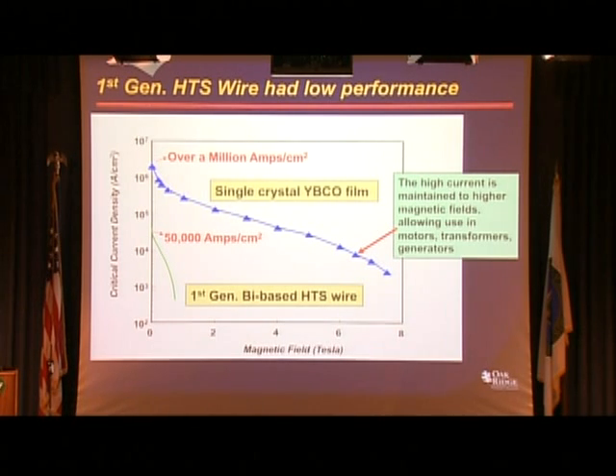What we wanted was a blue curve, which is really of a YBCO film deposited on a single crystal strontium titanate. You can see that it had a current capacity of over 1 million amps per unit cross-section, which sustained itself in high applied magnetic fields, which is important for most of these electric power applications. So the question is, how can we improve the performance of the wires?